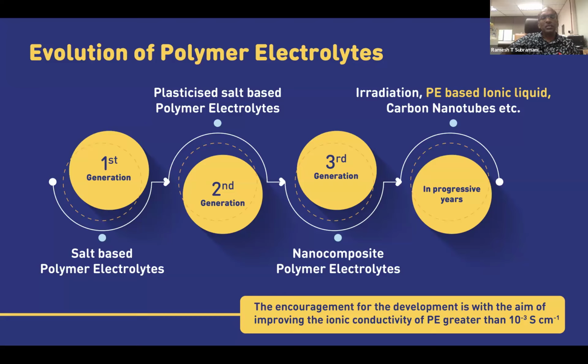So what happened for the second generation is the conductivity can be enhanced, but the material becomes too soft. So the mechanical properties deteriorated. This becomes difficult for us to handle and to fabricate devices. That's where the third generation polymer electrolytes come, where you use nanocomposite materials like aluminum oxide, silica, and zinc oxide to improve the ionic conductivity. These nanocomposites not only increase ionic conductivity, at the same time, they also can improve the aging effect. When I say aging effect, it means they can retain high ionic conductivity over a prolonged time. In progressive years, we are using radiation and also adding ionic liquid and carbon nanotubes.